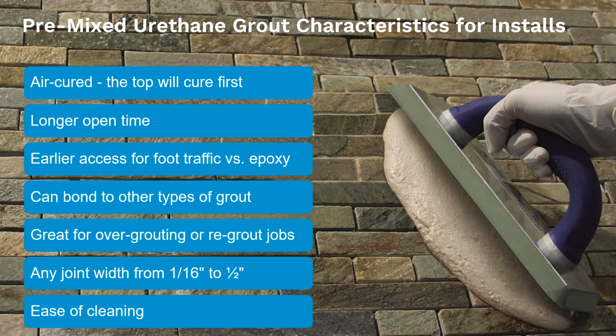Pre-mixed urethane grout characteristics as part of installation. It is air cured, so the top will cure first, and then it cures as it goes down to the bottom. It has a longer open time. It has earlier access to foot traffic versus epoxy. It can bond to other types of grouts. It's great for over-grouting or if you need to regrout a job. Any joint width from 1/16 to 1/2 of an inch, and it is easy to clean.